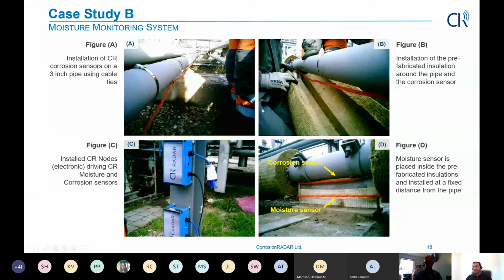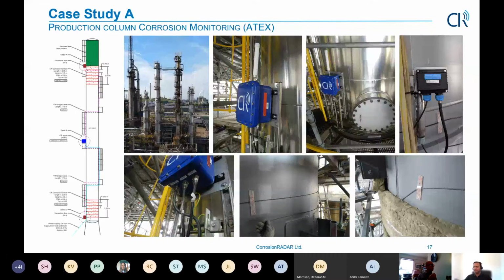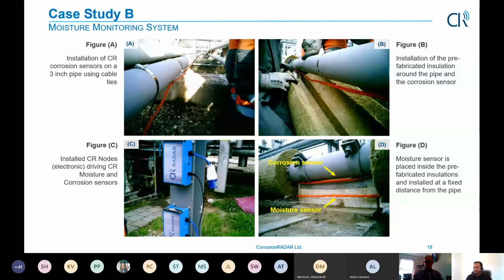Again, this was a trial where the most important picture is figure D, where on the bottom right you see moisture sensors and corrosion sensors. In this case, they are installed one below the other, but it need not be the case. They can be installed together. But in this case, the moisture sensor was more likely to catch water if water is added, so we put it right at the bottom. It's installed in a very easy manner. Normally it takes half a day for installation. In the previous case, it took half a day for the corrosion sensors and moisture sensors to be installed. Again, similar case here. So it's not a very time-consuming activity if it is planned well.